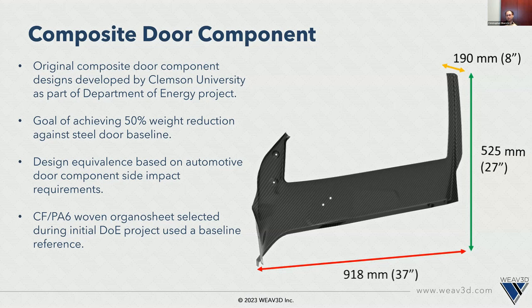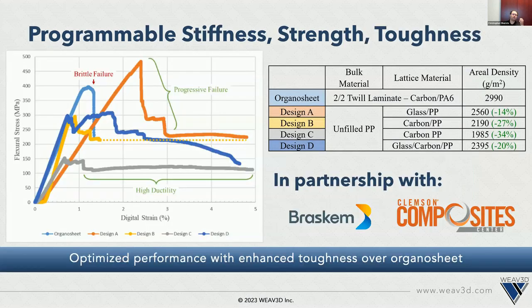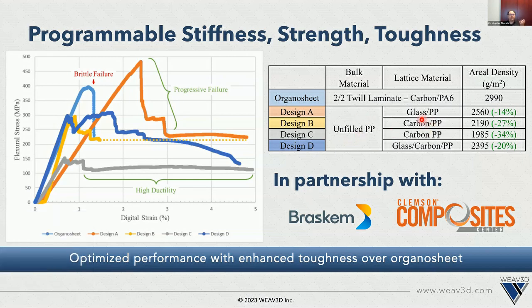So we came into this project in partnership with Braskem, and we wanted to propose an alternative: can we redesign this part in polypropylene, but using a lattice structure to optimize the amount of material used? Where we started was some flat panel studies looking at different combinations of plastic material and lattice reinforcements. So different types of lattice, glass, carbon fiber, mixes of the two, as well as different spacings of patterns. These two carbon fibers that you see here, one is a high density, one is a low density spacing. And we plotted these in a stress strain curve versus the reference organosheet material.